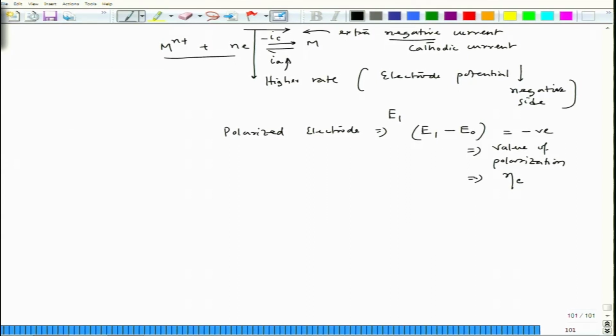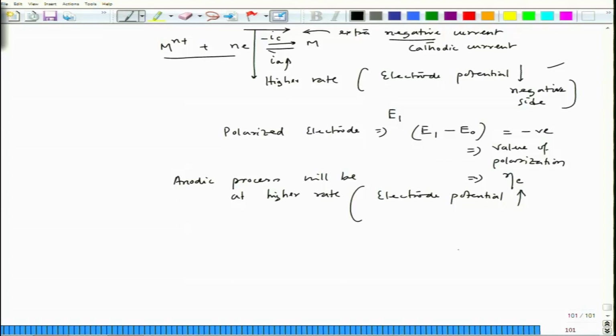Similarly, if we supply anodic current, then this anodic process will be at a higher rate. The way we have discussed here, the electrode potential would increase from the standard value or the equilibrium value, and we also call it a polarized electrode, and at that time the potential goes to E2. So, E2 minus E0 is a positive quantity, since the potential has moved to the positive side, because we are actually taking this oxidation process at a much higher rate. So, this becomes the value of polarization.